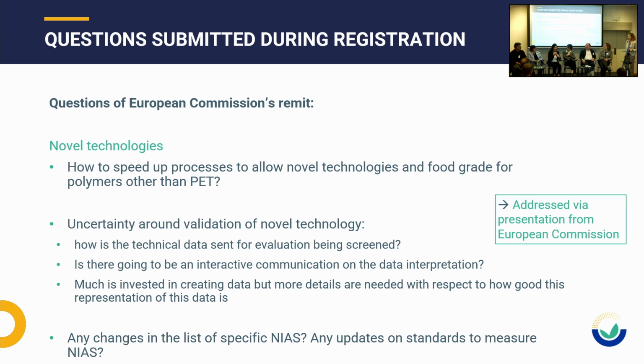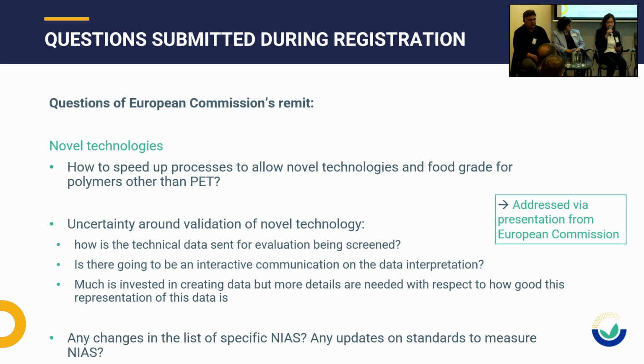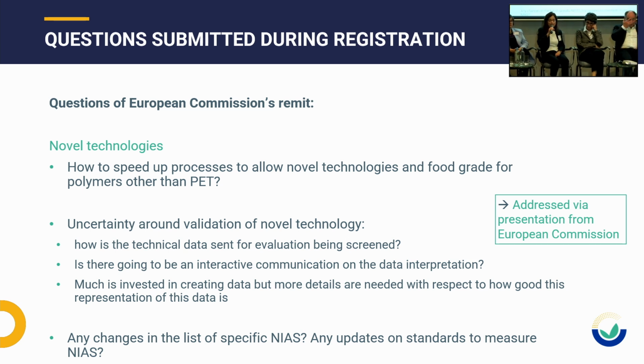Please, Eugenia. Thank you for the question. Yes. After the artificial contamination of the flakes with surrogates, we know from the data we had up to now that there is surface contamination. This surface contamination shall be removed before going inside, because this surface contamination does not represent the actual contamination of PET. So this should be removed, and water is not capable of removing all these organic surrogates used. So there is a rinsing. The applicant may perform washing using, for example, detergents or alkali, or rinsing with, for example, 10% ethanol.